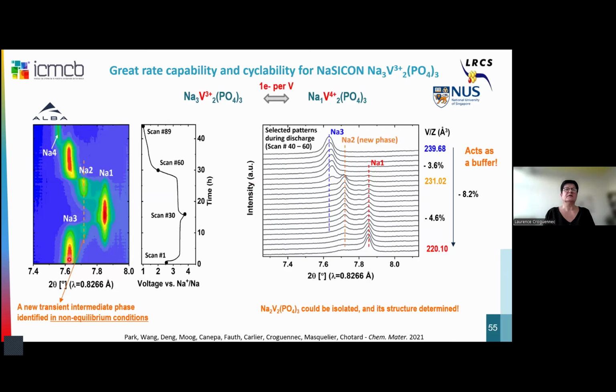And as you can see here, when we move from Na3 to Na1, we have an intermediate phase, Na2, that is observed when we are in non-equilibrium conditions. And you can see also that we do not have a symmetric behavior between charge and discharge. And this Na2 phase could be isolated in synchrotrons, but could not be isolated when we recover the material from the battery. It's a metastable structure, and despite that, of course, this structure could be determined.